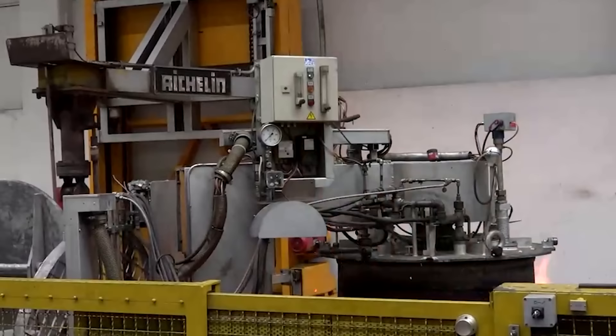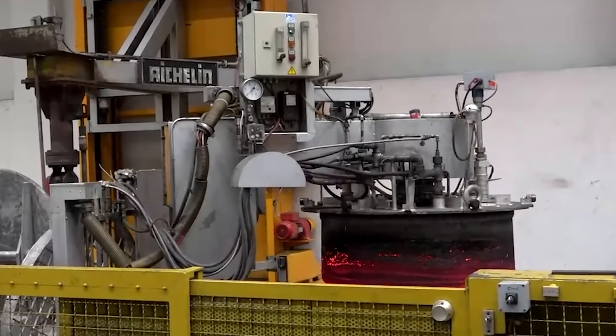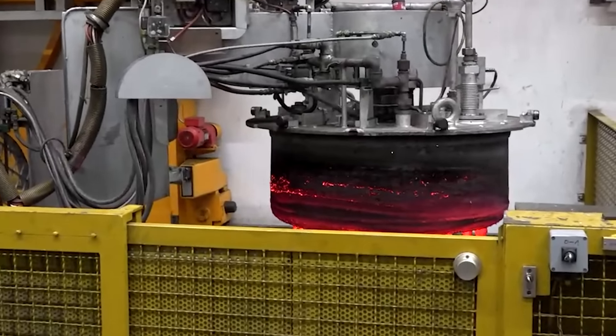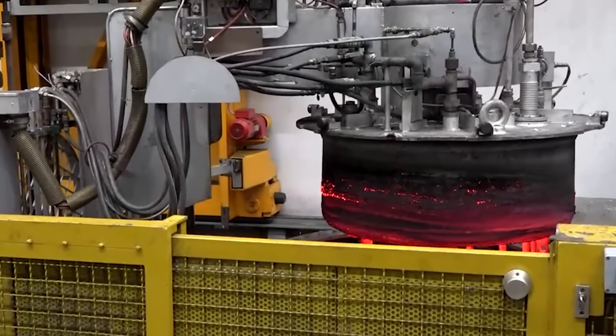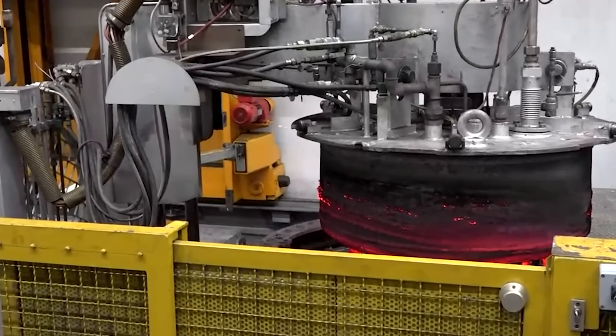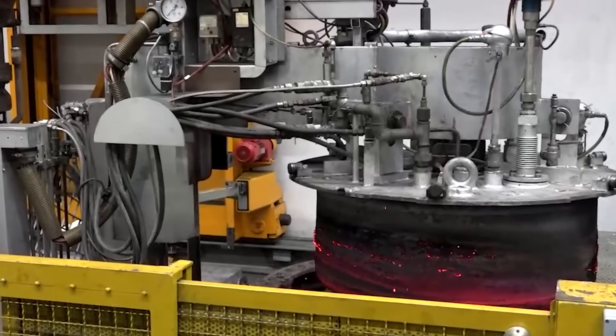The parts get heated to 890 degrees centigrade, come out of the heat, go into the salt water brine bath. And then they're left for about seven hours to cool down. Then we get the hardened parts come back out again.